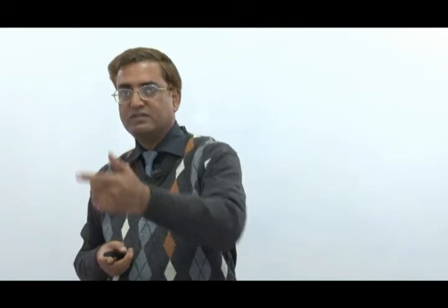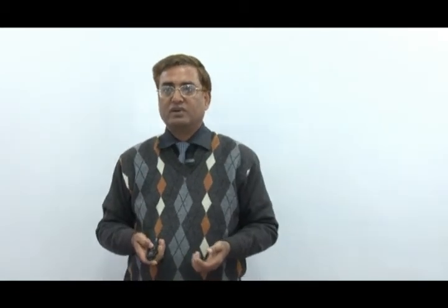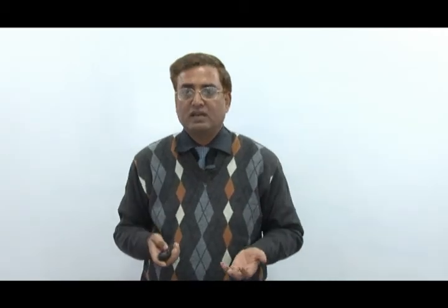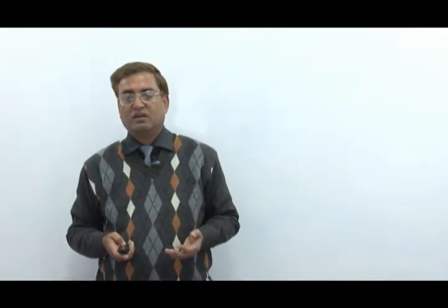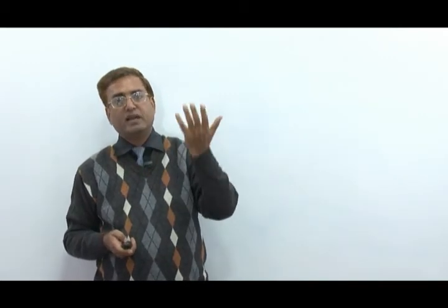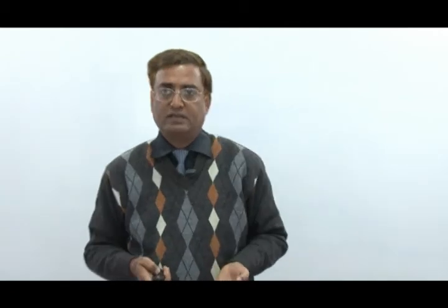Whereas this figure shows the variation of RS, that is the die stress, with friction at different reductions, and it is clear that RS increases almost linearly with increase in reduction as well as friction. The trend obtained from this figure again shows very close agreement with the earlier results, which were carried out way back in 1985 by Gunasekar at IIT.